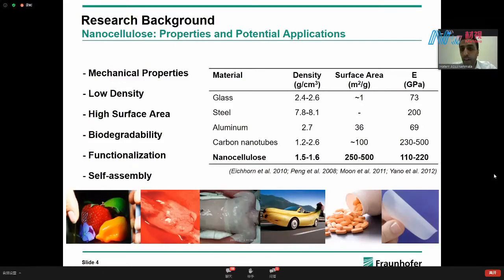What's very interesting about nanoparticles in general is the very high surface area. We're talking here about 250 to 500 square meters per gram. And this high surface area is what makes nanoparticles way more effective than macroparticles such as cellulose fibers. Also, nanocellulose lends itself to a wide range of surface modifications due to the abundance of hydroxyl groups on the surface, which make them easy to functionalize, making many kinds of functional nanocellulosic materials. And due to their size and surface charge, nanocellulose can form one-dimensional, two-dimensional, and three-dimensional liquid crystalline structures, which are very interesting for optical applications.